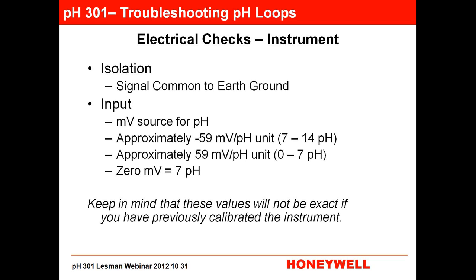But you can also hook up a millivolt generator to make sure your input card is working correctly, and you generate, say, minus 59 millivolts should be 6 pH. I'm sorry, minus 59 millivolts should be 8 pH, minus 118 should be 9 pH, etc., and then below 7, the opposite. If you don't have a millivolt generator and you just want to take a quick swag at it,